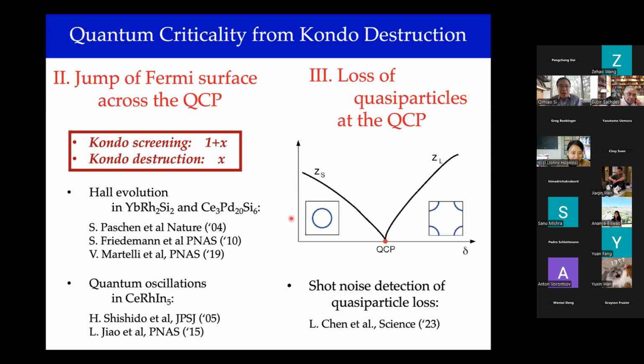A few other features that I want to just very quickly mention, this has been talked about in the past, but one thing that happens is that if you have the Kondo singlet that's formed on the paramagnetic side, you have these composite heavy fermions which are generated in the excitation spectrum, so the Fermi surface becomes large. Well, if the other side is Kondo destroyed, these heavy quasiparticles are absent, and the electron count is such that the Fermi volume equals x, and there's a jump of the Fermi surface that has been studied very extensively by Hall measurements and quantum oscillation measurements.